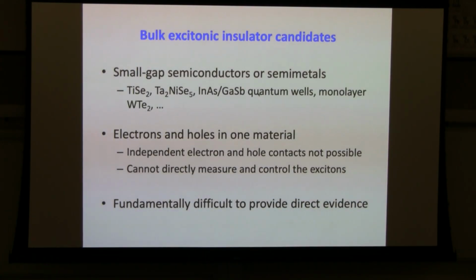All right, so there are not many, but several excitonic insulator candidates in bulk form. They are typically small gap semiconductors or semi-metals. I list some of the examples here. In this type of materials, the electron and the holes all live in the same material. So it's very hard to make independent electron and hole contacts. I would say that it's actually impossible to make independent electron-hole contacts. And therefore, you cannot really directly measure the excitons. You also cannot control the excitons, such as their density and their chemical potential. So for this type of material, it's fundamentally difficult to provide direct experimental evidence of an excitonic insulator.